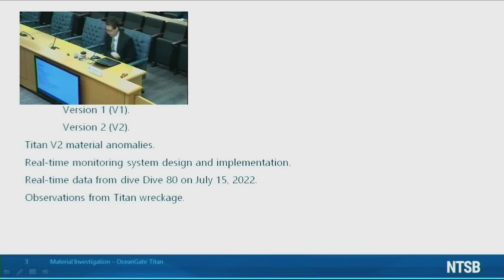This hull was manufactured using a multi-step co-bonding process that was different than the V1 hull in that it contains multiple adhesive bonded joints. We were able to examine some material from the manufacturing of the V2 hull, and we found several anomalies within the composite and the adhesive joints, including waviness, wrinkles, porosity, and voids. I'll show examples of those as well as some features consistent with rubbing damage at one of those adhesive joints. Next, I'll recap the Titan's real-time monitoring system. I'll talk briefly about the principles behind these methods and review how OceanGate implemented them on Titan.